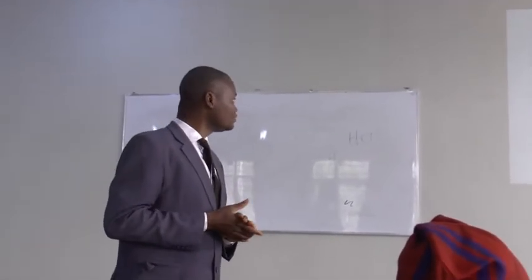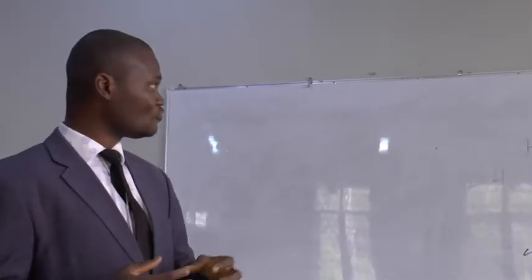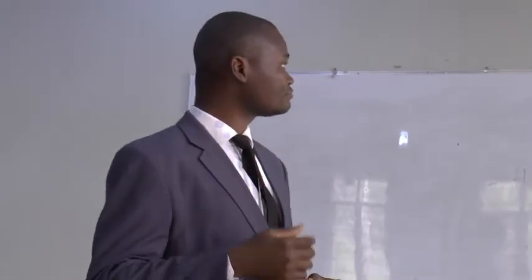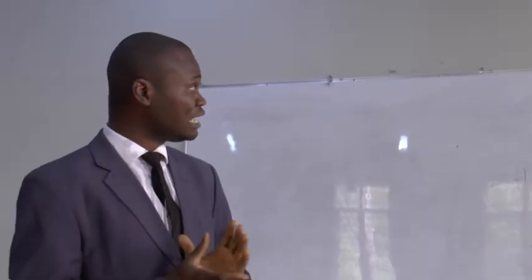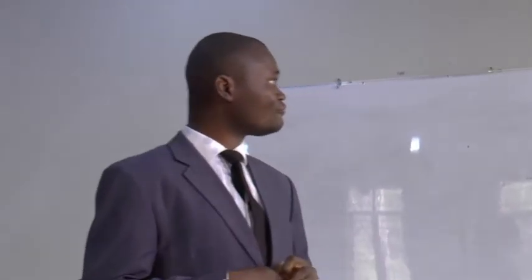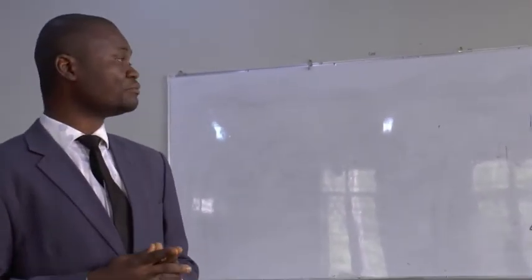Then this is the scatter diagram for experimental responses, and also the prediction of the models for both yield and iodine number. We use some error functions to evaluate the deviations of the model from the experimental results, and these are the values. The next slide, please. For the performance of methylene blue adsorption, we obtained 136 milligrams per gram for the adsorption capacity, which was equivalent to a 90% reduction in the methylene blue concentration at equilibrium.